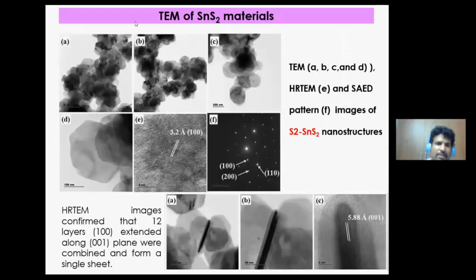Next, with only oleylamine, we got a mixed structure. With the addition of oleic acid and octadecene, we got the leaf-like structure, that is, the lotus leaf-like structure, and we got an idea to remove the octadecene to check the output. So the oleylamine and oleic acid combination shows a beautiful hexagonal structure with a controlled surface. In the previous case, you can see the orbicular nature of the particle. So with this, we can conclude it is a disc-shaped material.